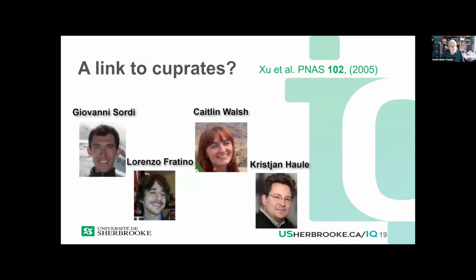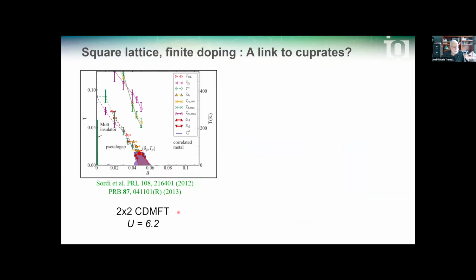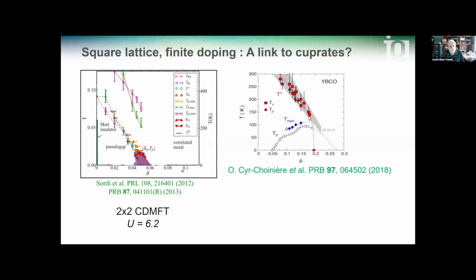Let me get back to the theme here. These are now 2x2 cluster dynamical mean field calculations for this value of U at finite temperature on the square lattice, again plotted as a function of doping. You see the Sordi transition at low temperature, and above the critical endpoint, you observe the Widom line and various crossovers. Since crossovers are defined in various ways, some of these crossovers, like the Knight shift, occur above the Widom line. You see, however, that all the crossovers end abruptly instead of extrapolating linearly to T equals 0. And this is what was observed experimentally later, as shown on the right-hand side. The crossovers just drop.